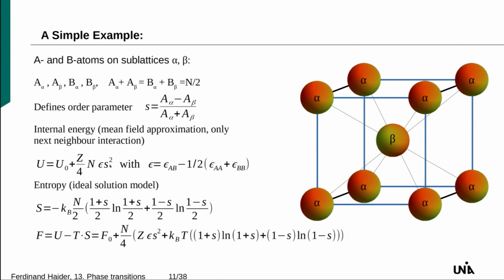There's one further assumption, the so-called mean field approximation, or two further assumptions. First, I assumed that there are only next neighbor interactions, so only from the corner side to the body center side, not across the lattice constant here. That's the nearest neighbor interaction, but that's very simple to generalize. And this mean field approximation, what does this mean?